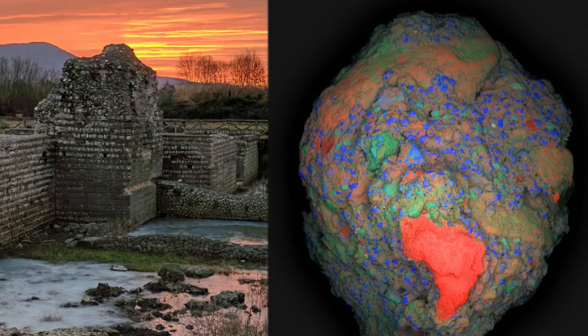Previous support for this hypothesis was found through the examination of other Roman concrete samples that exhibited calcite-filled cracks. To prove that this was indeed the mechanism responsible for the durability of Roman concrete, the team produced samples of hot-mixed concrete incorporating both ancient and modern formulations, deliberately cracked them, and then ran water through the cracks. Sure enough, within two weeks, the cracks had completely healed and the water could no longer flow.